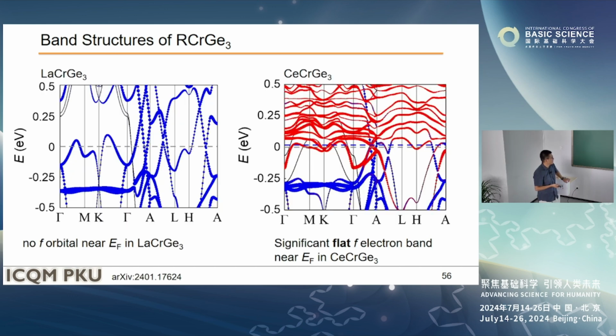Okay, our collaborators also did some band structure calculations for lanthanum and cerium. So basically, this is DFT, right? Not DMFT. But still, you can find some signatures of active f electrons. For cerium, you see a very strong distribution of the flat band on top. So we have a significant f band near the Fermi level.